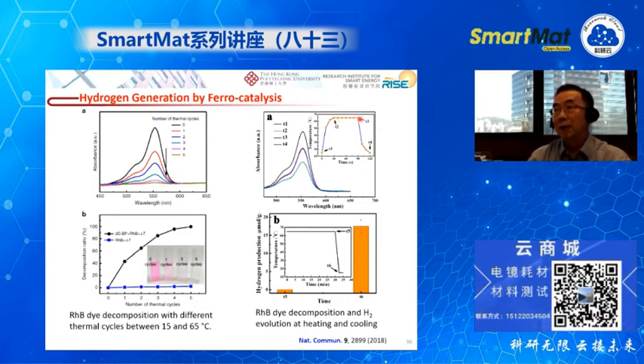And when you decrease the temperature from 65 down to 15, then again we observe the decomposition phenomena, and that is the feature of the pyroelectric material, because the polarization can only change when you change the temperature. If the temperature is constant, there's no change in the polarization, and therefore there's no pyrocatalytic effect.